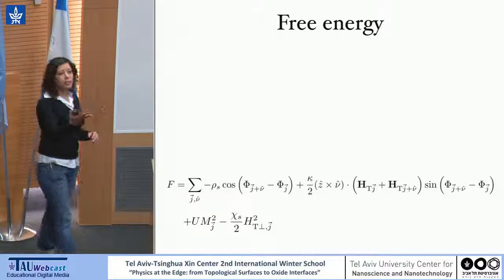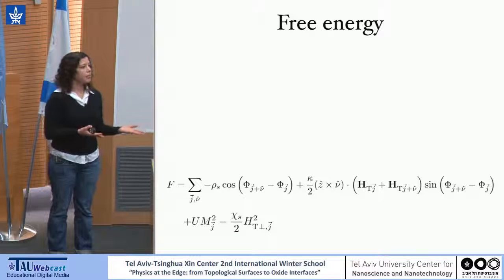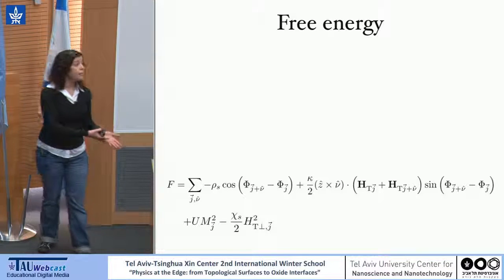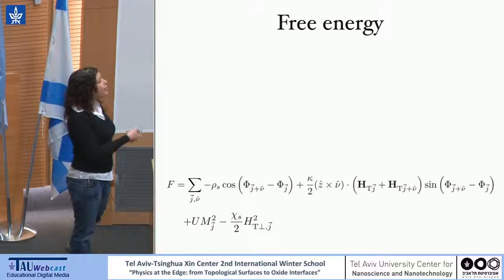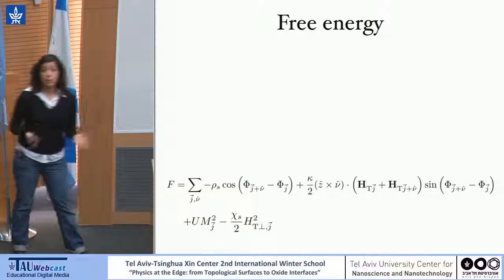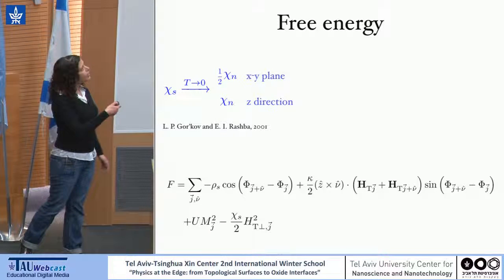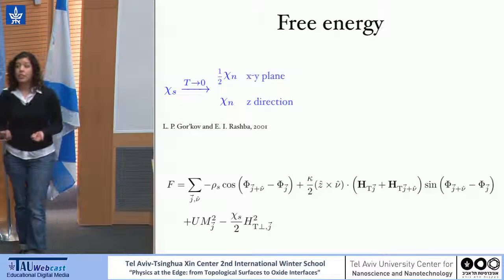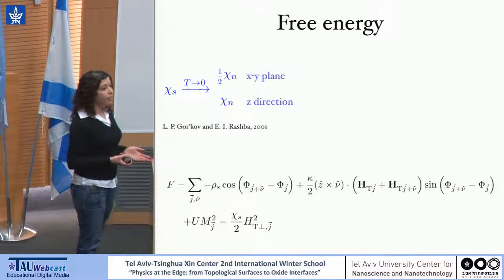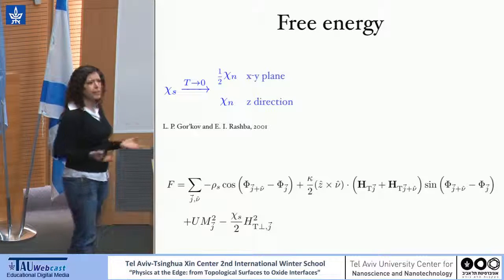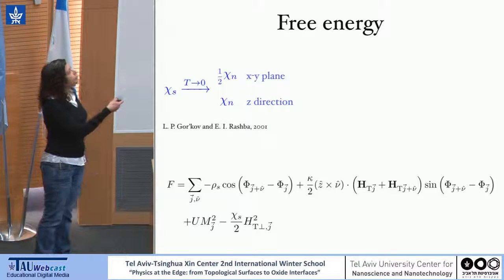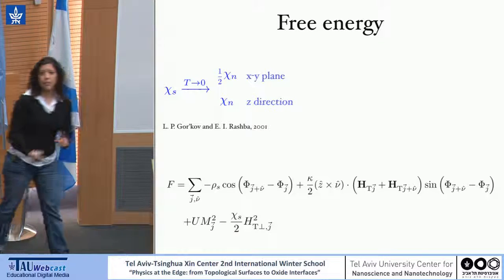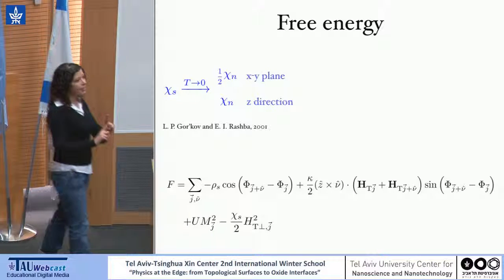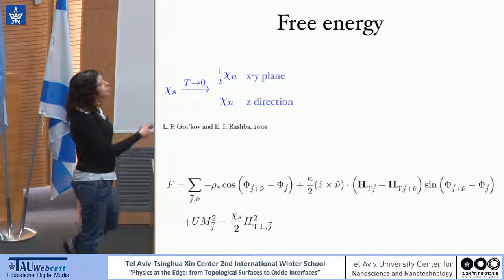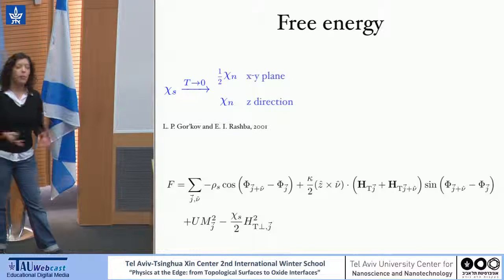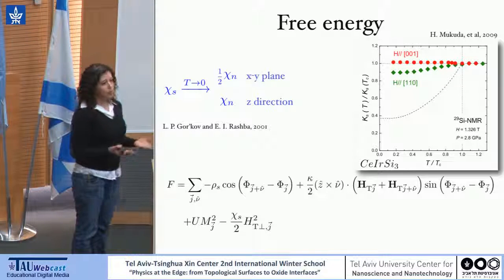Now, we usually know that in a regular superconductor, spin susceptibility goes to 0 deep in the superconducting phase. And that is another unique thing for systems with spin-orbit coupling: magnetic susceptibility doesn't change much inside the superconducting phase. We can see that it can get a bit anisotropic. It will be different for the xy plane versus the z direction, if you assume that the spin-orbit vector is in the z direction. However, it's still very far from being 0. It's very close to its normal value. And that's something that people measured.